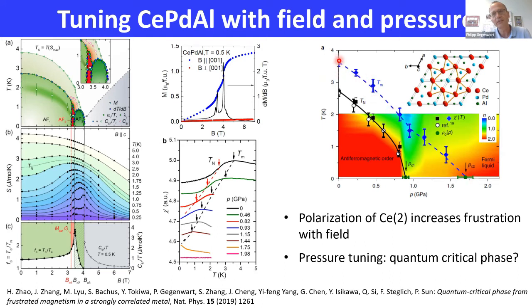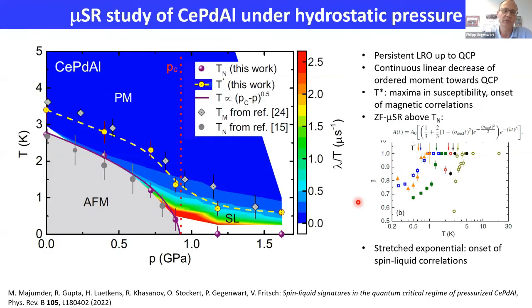this temperature, which is an indicator below which the spin liquid correlations may start, disappears at a critical pressure which is almost twice as large as the critical pressure for the long-range antiferromagnetic order. Also we see here as a false color in this phase diagram that the electrical resistance exponent in this intermediate pressure stage is about 1.5. So we see non-Fermi-liquid behavior in this pressure region between the two critical pressures for cerium palladium aluminum. And that was the motivation to look more carefully now with microscopic probes at what happens under pressure in cerium palladium aluminum.